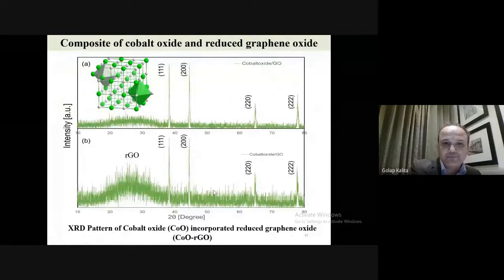Then what we did is that we combined this with cobalt oxide, and cobalt oxide can be in two different forms. This is CoO. There is Co3O4 also, but we got the CoO phase with the graphene oxide. So we combine it with metal oxide. Metal oxide combination is important because it can boost your reactivity, or you can get a redox supercapacitor. So we tried this type of thing.